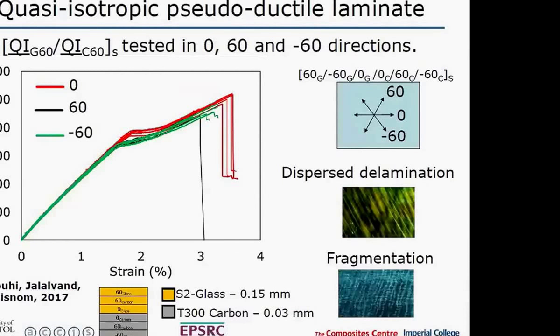And that's another very interesting phenomenon which I could spend the whole time talking about, related to hybrid effects. One of the other things we see with these hybrid composites is that we can see an increase in strain at failure in the carbon, and that's because the glass adjacent to it actually inhibits the formation of critical fiber clusters. We get an increase in the strain at failure, which can be quite significant. It can be at least a 10% increase in the strain at failure. And in this case here, in the 0 configuration, that 0 carbon is next to a 0 glass. And that produces a higher hybrid effect than if it's in the other configuration. The 0 is actually next to a 60, and therefore it doesn't get quite so much constraint from the adjacent ply, and you get that difference in the failure strength. So that's a whole other interesting thing that's come out of this program, understanding hybrid effects and how we can take advantage of them to actually get higher strains at failure in the carbon in these hybrid configurations.